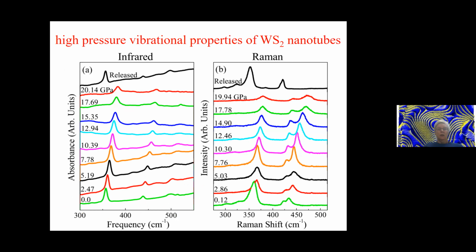Okay, so here are the results. We have infrared as a function of pressure on the left-hand side, and Raman scattering as a function of pressure on the right. And like I said before, it's really this infrared that is the crown jewel of the compressed beamline. So there are some well-known vibrational modes here. There's this E1U, doubly degenerate interlayer mode, the A2U interlayer mode. And then Raman scattering also has a variety of features that harden with increasing pressure.